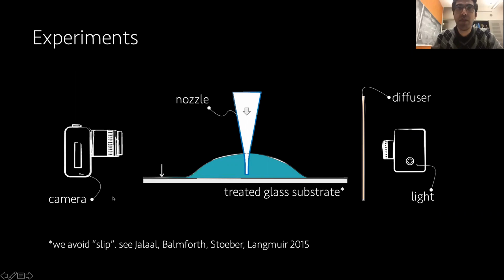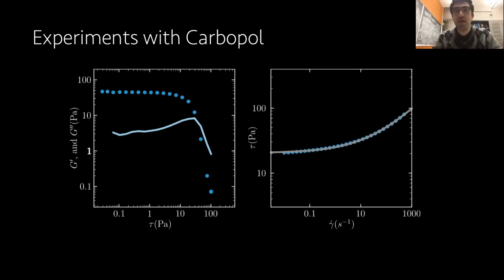Our experiments were fairly simple to do. We have a camera on the left, and diffused light on the right. We use treated glass surfaces to avoid slip. As you know, these viscoplastic materials also slip on the surface. What we've done is use glasses that have positive charges on top. If you're interested in that, you can have a look at our Langmuir paper. We inject fluid through a nozzle, like 3D printers work. The droplet grows and spreads, and we look at the final shape. Our material was Carbopol, the beloved simple fluid that people in the yield stress community use.